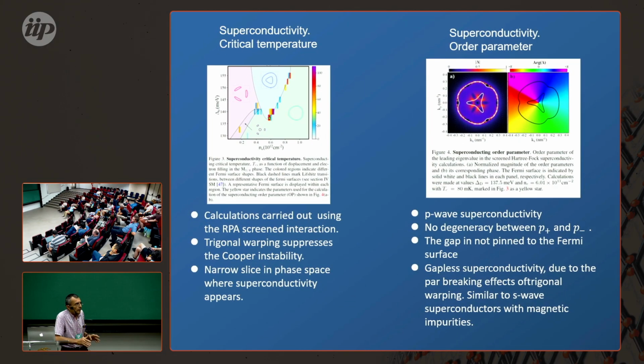That is due to the long-range Coulomb interaction, both in 3 and in 2 dimensions. In 3 dimensions, it's discussed even in the book by Mahan. Then we had to resort to this RPA-like combination of terms, which is a bit like GW0 in terms of band structure calculations, and we recovered superconductivity. But definitely, even if you go beyond Hartree-Fock, you don't have a Cooper pair singularity. So there was no reason, and there should be some threshold beyond which there is no superconductivity. It should be a first order phase transition, because if you don't have the logarithmic singularity, there is no divergent susceptibility which guarantees that you will have superconductivity as a function of a parameter being increased slowly. So this is just a numerical result, which we don't fully understand, but definitely there is superconductivity.